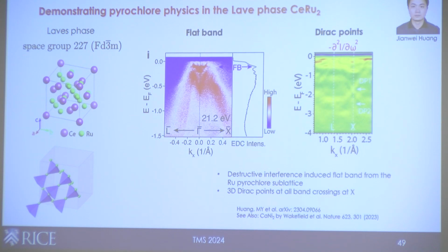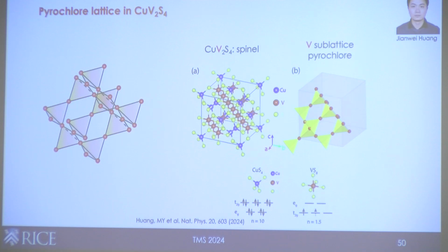So we try to look for other materials that could give you a better flat band. The next one we encountered is a spinel material. It has copper, vanadium 2, sulfur 4. It's quite complicated, but if you strip away everything else, leaving the vanadium, you see the vanadium sublattice forms this pyrochlore lattice. Why is this better?